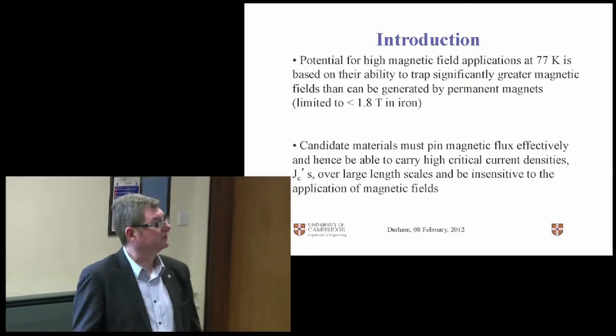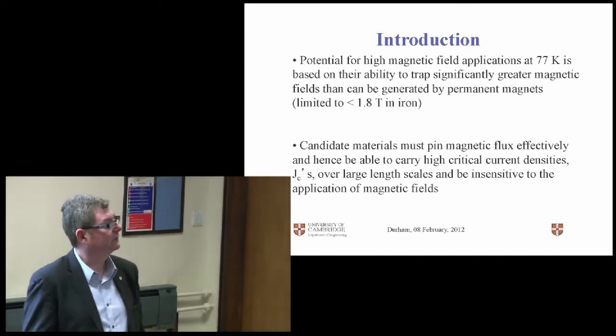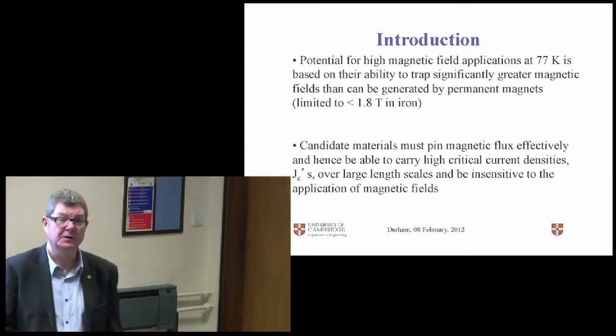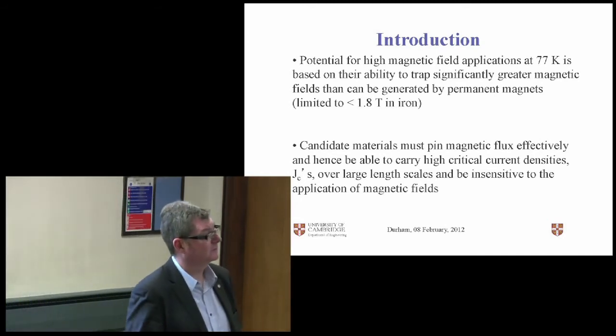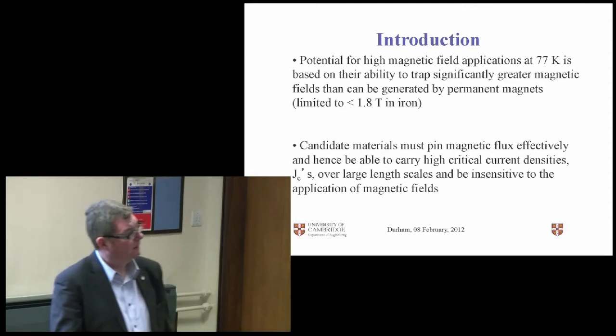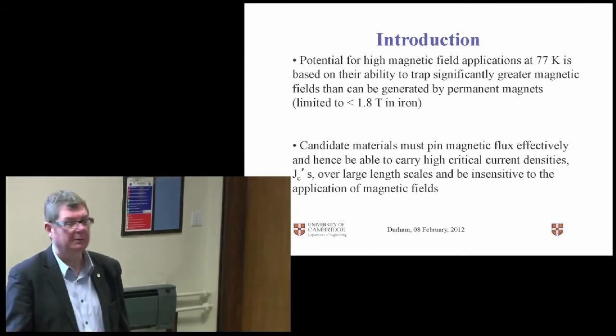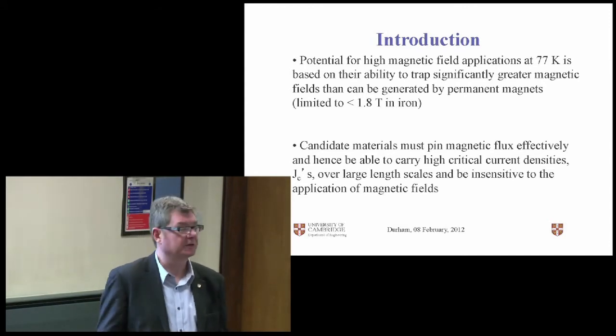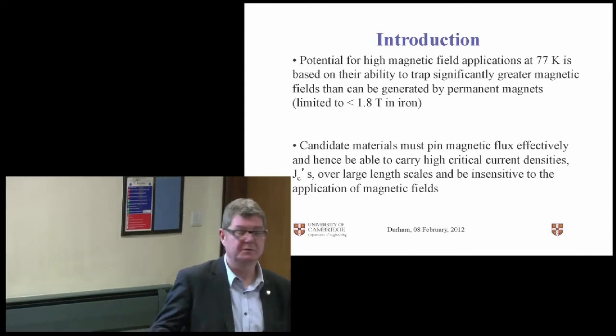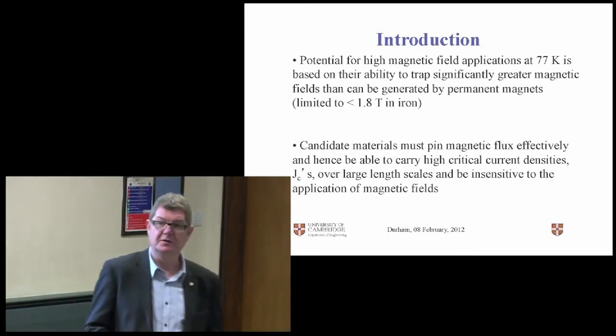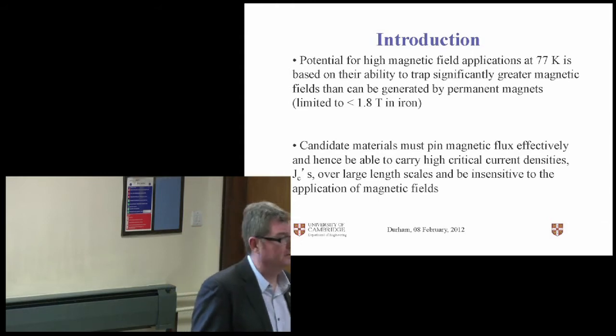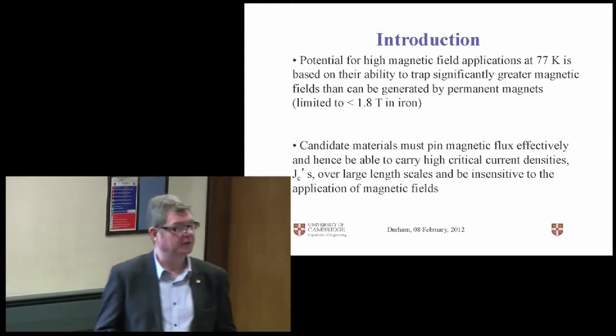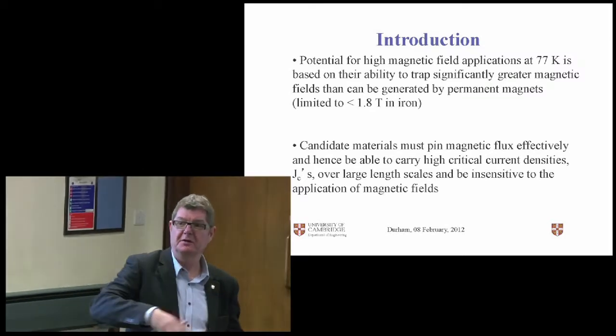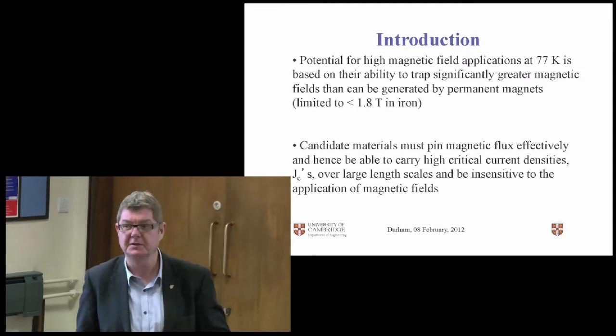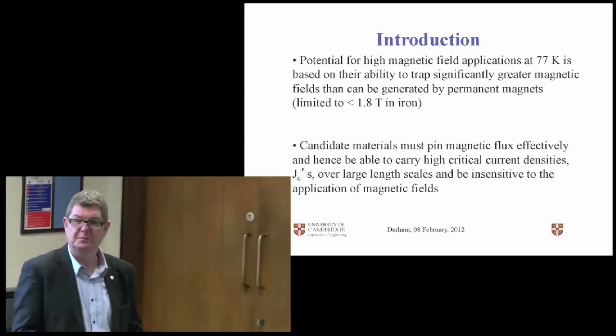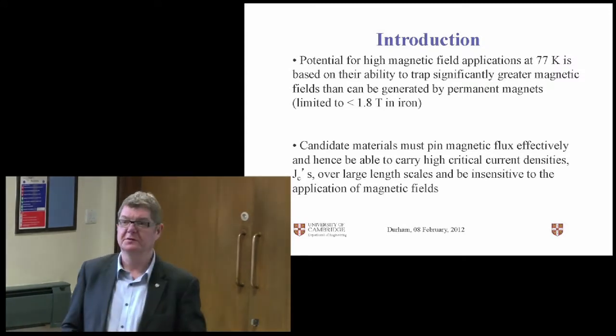Okay, so having established the potential, we need to explain why materials can generate high fields. Well, fields always come from current or moving charge, either spins on sites or charge with linear momentum. So essentially, we need to explain where we get large currents from, and they come from flux pinning. So magnetic flux in superconductors exists in the form of long, thin, quantized filaments, Faraday's lines of force, effectively, the kind of lines that 8-year-old children associate with magnetic fields when they sprinkle iron filings on the top of a bar magnet. Of course, field in space is a continuous variable, but you get this notion of fields existing as individual lines. So in superconductors, they really do.